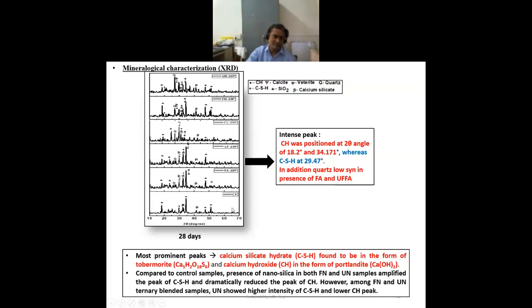Now this is my control paste. You can see I'm getting some peaks. The moment I add the secondary cementitious materials and then the nanoparticles, you can see how my peaks are getting intense. More and more peaks are available for the calcium silicate hydrate, the quartz, the calcite, the vaterite. The intensity is increasing, so that signifies more hydration is happening within the cementitious system.